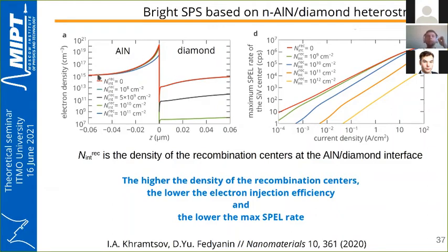If there are no recombination centers, the electrons in diamond have a very high density. But if we put interface defects, they can capture electrons and holes from both aluminum nitride and diamond, which eventually leads to very low electron density in the diamond, and our single-photon source will be very dim. That can be seen from the right plot.